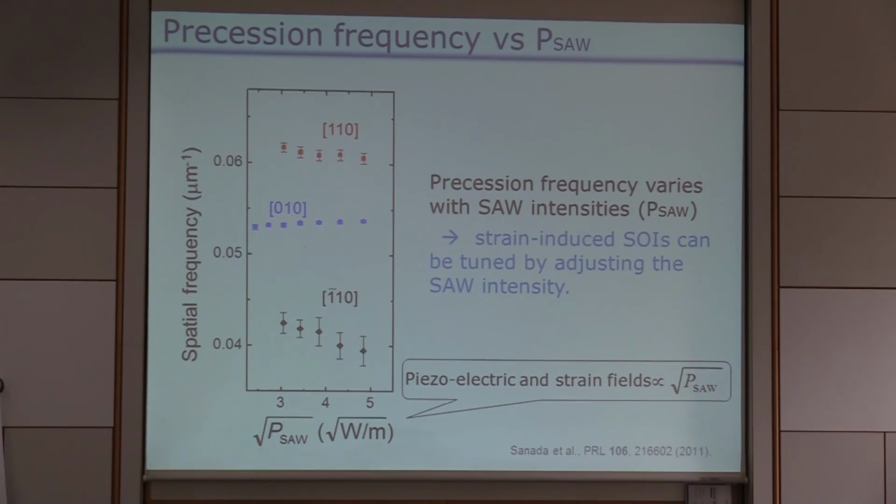Maybe, if I remember correctly, if you have the dots, the hydrostatic strain is 0 at the points where you confine the electrons in the dots, because you just have the piezoelectric potential. So there is a phase difference between the strain dots and the piezoelectric dots. And where you have the piezoelectric dots, you don't have hydrostatic strain. In the dots? In the dots, yes. Okay. And maybe this is one of the reasons why you actually have such a... Maybe. Thank you.